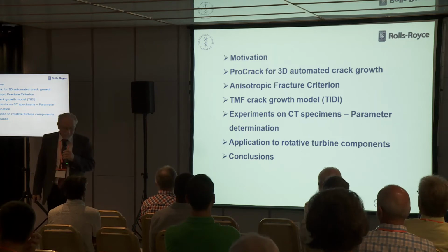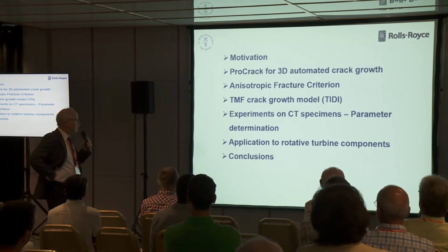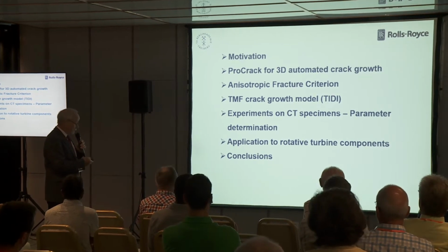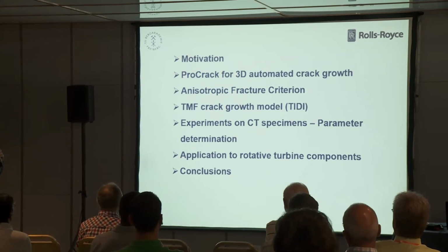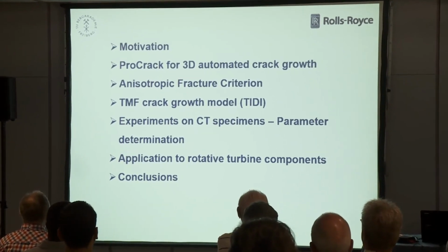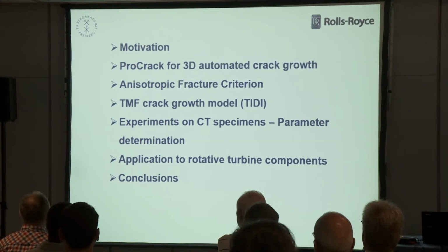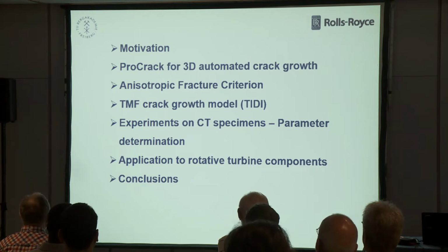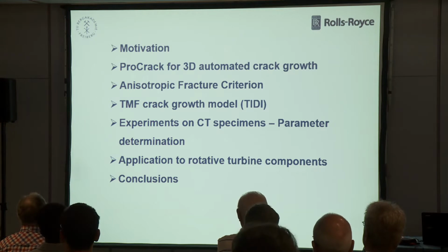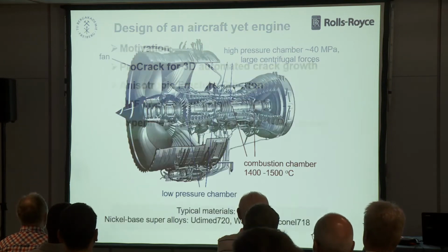So, I want to bring a motivation at first to introduce this specific problem, and then shortly I recap our finite element code ProCrack, which is able to simulate 3D fatigue crack growth in an automatic manner. Then I come to the very topic, the anisotropy of the fracture behavior in this special alloy, and we have to combine it with the TMF crack growth law, which is established at Rolls-Royce. There experiments have been done on CT specimens, and we could simulate them, to validate and identify the parameters of our model. And finally, we applied this model to a typical component of a rotor of a jet turbine. And then I close with conclusions.